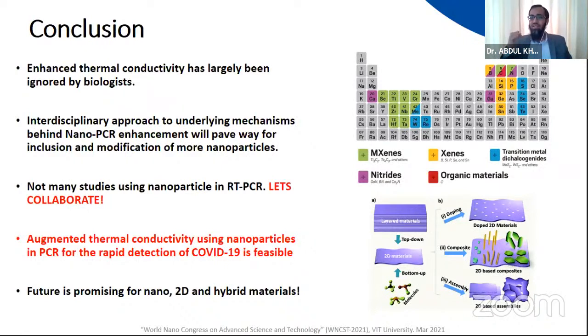Number three, in terms of cycles, you can gradually decrease the number of cycles from 40 to 35, 30, 25. So we managed to see the yield until 25 cycles. In case of positive control, there was visibly no yield at all. But with the use of nanoparticles, we could see yield happening even at 25 cycles or even 20 cycles in some cases.